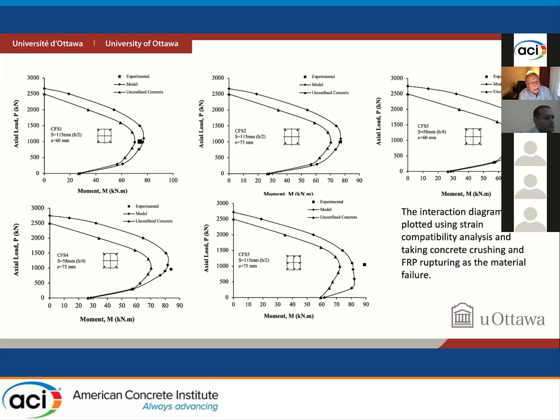Our failure envelope was defined by either crushing of concrete or rupturing of FRP. As I said, in our test, we did not observe rupturing of FRP, but these interaction diagrams were plotted for that condition. And these are nominal interaction diagrams. And obviously, we have to use a phi factor and reduce the capacity by 25% to get design capacity. So design capacities will be well inside of these curves.